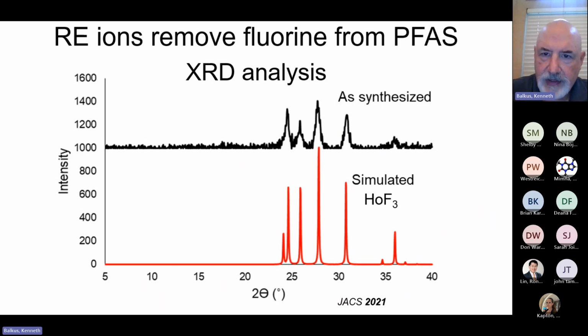So now, one thing I should point out is that the linker, while it is important with regards to the overall structure that you end up with, is not required, of course, to remove the fluorine from the organofluorine, whether it's PFAS or fluorobenzoic acid. In fact, if you just take holmium ions, holmium nitrate, and you boil it up in DMF with your PFAS, you make holmium fluoride. Okay, and that's very easy to see by X-ray diffraction.